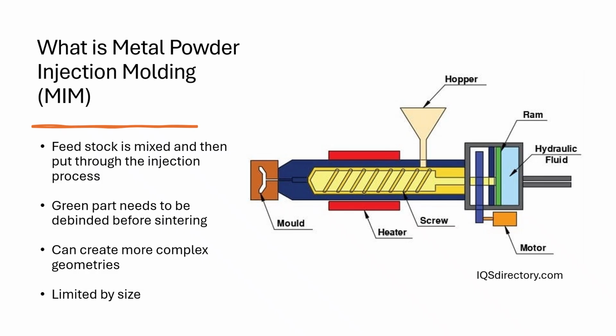Here, the brown part is placed in a furnace, and the part is heated up to a high temperature. At this point, the part will begin to shrink as it fills in all of the spaces where the binder used to be. This shrinkage is something that definitely needs to be accounted for during molding to create the part at a greater scale in order to account for this shrinkage. Now, one of the major benefits of this process over other processes is it can create much more complex part geometries. However, the process is limited by the size of the parts that it can create.